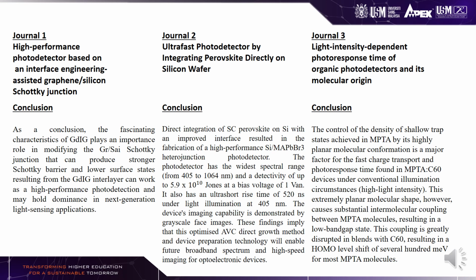The conclusion for the third journal: the control of the density of shallow trap states achieved in MPTA by its highly planar molecular conformation is a major factor for the fast charge transport and photoresponse time found in MPTA carbon-60 devices under conventional illumination circumstances of high light intensity. This extremely planar molecular shape, however, causes substantial intermolecular coupling between MPTA molecules, resulting in a low bandgap state. This coupling is greatly disrupted in blends with carbon-60, resulting in a homo level shift of several hundred millielectronvolt for most MPTA molecules.